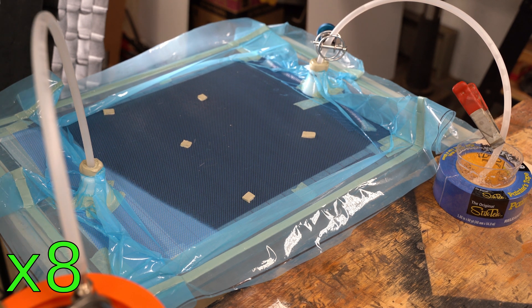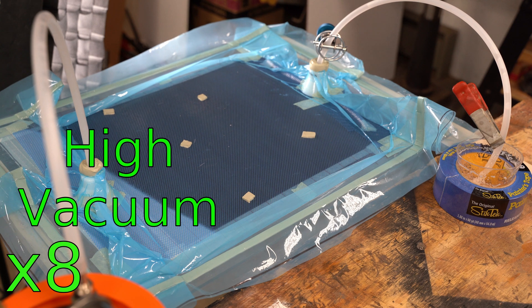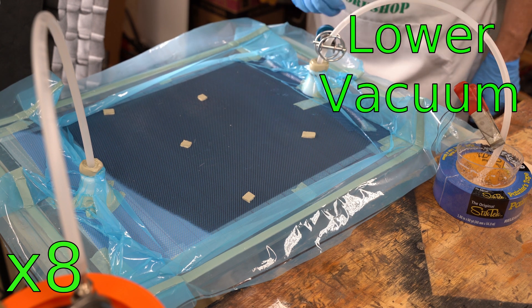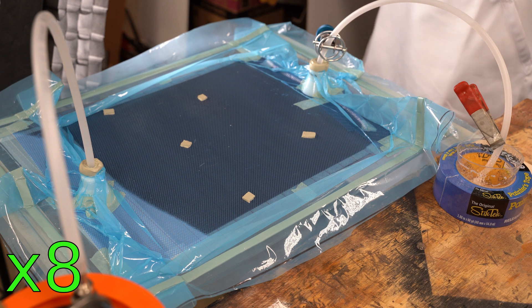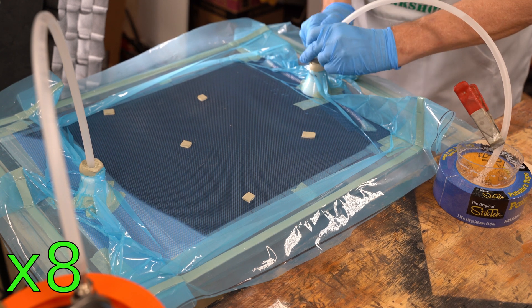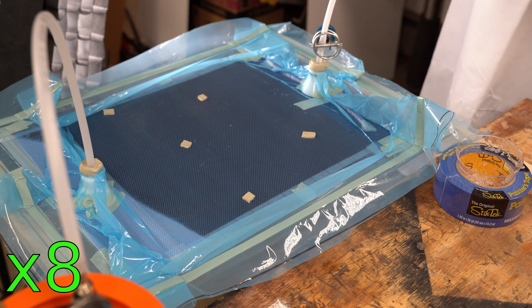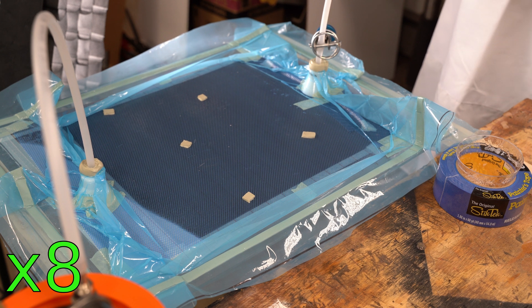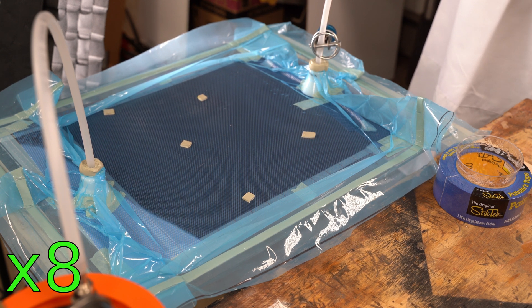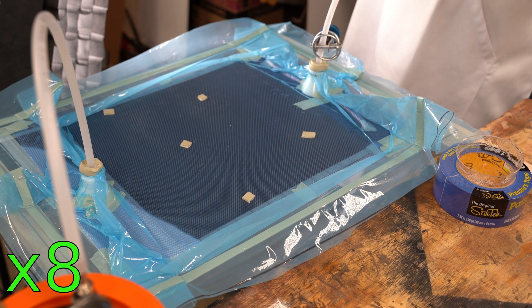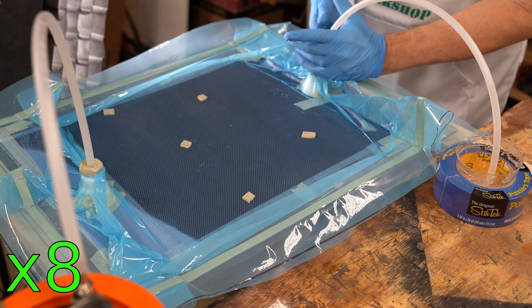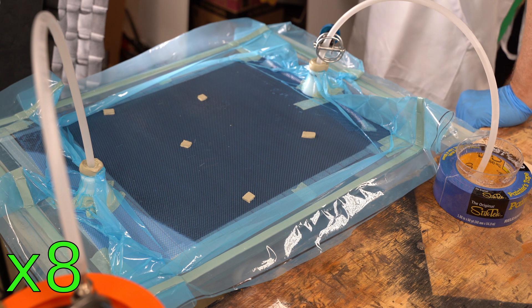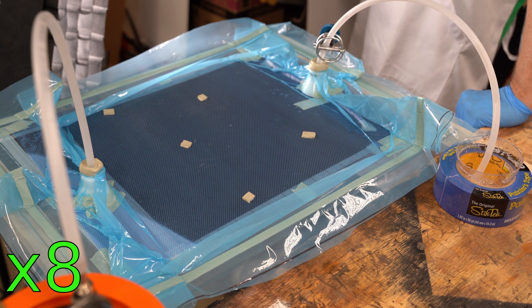There is a vacuum gradient across this part. There is very high vacuum there at the output port where it's pulling the vacuum. There's a much lower vacuum over toward the input side where I've got the clamp. And just as an aside there I had played with that clamp valve again. The reason for that is I had noticed a little more epoxy had run down toward the clamp. There was about six inches or so. So I opened up the clamp and let that run in. And then I thought you know I'm not sure I have enough epoxy to fix this. So I lifted the tube up in the air to try to get just a little bit more epoxy that was in that tube to run down. And then I'll let that into the part and then clamp it again.